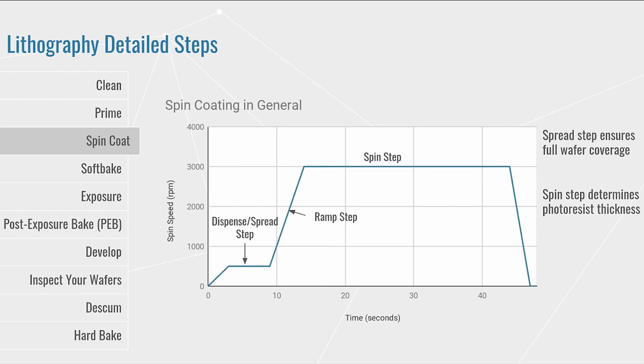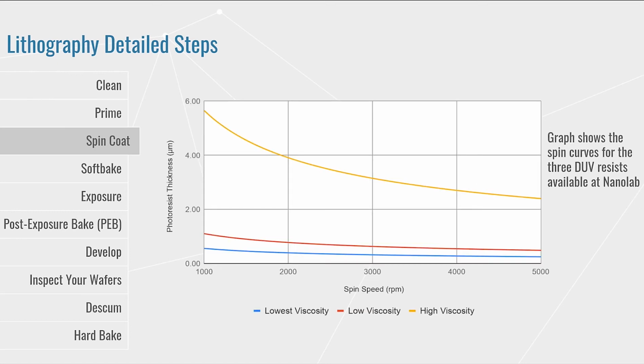A slower speed yields a thicker resist layer, and a faster speed yields a thinner resist layer. This graph shows spin curves for three different photoresists. The graph is created by plotting the photoresist thickness versus the spin speed during the spin step. These plots are used to find the appropriate spin speed for the desired photoresist thickness. Different photoresists with different viscosities will have different spin curves and different thickness ranges. The yellow line is from a photoresist with high viscosity, while the red and blue lines are from lower viscosity resists.